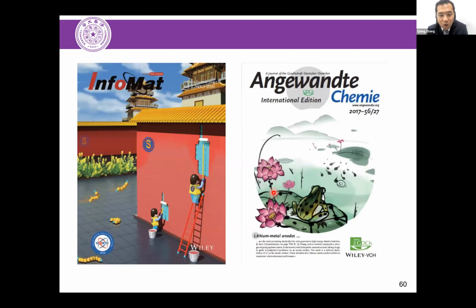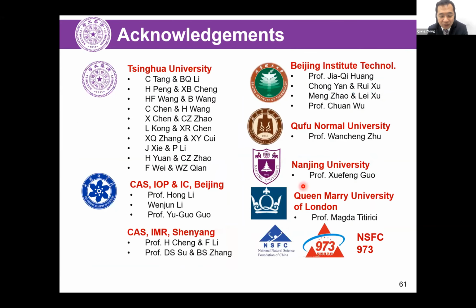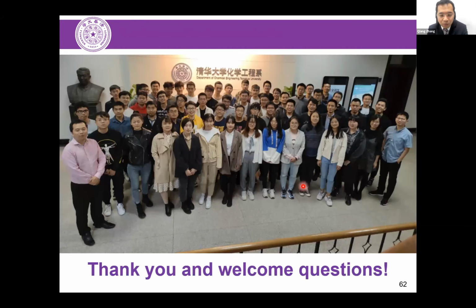So in contrast to previous research, based on my understanding, lithium metal anodes now have a lot of new coating films. That's quite different from before. And the addition of the composite host provides emerging energy chemistry to guide the lithium metal deposit to the right site. So this is quite important to get this metal anode deposited in a safe and reliable way. And the coming of lithium chemistry in contrast to carbon chemistry is quite important.